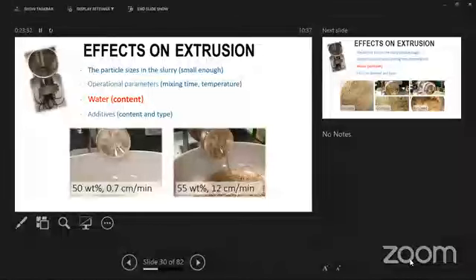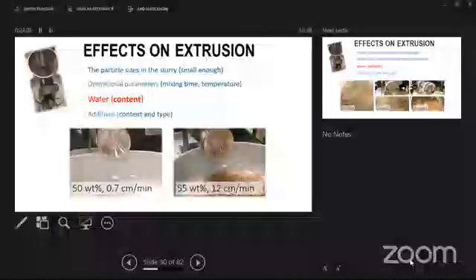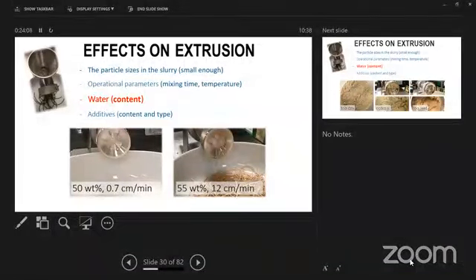And it was not even about water, it was just about humidity at a certain amount. That humidity should be at a certain level. So that person, unfortunately, had some personal problems and was on sick leave for 6 months. Not a single other technician at that company, with basically the same qualification, was able to make this experiment. So the company had to wait for 6 months before they were able to deliver these 4 tons, which tells how sensitive this manufacturing can be to very small things. And once again, it was not just 5% of water, it was the level of humidity in the making. This is a true story.